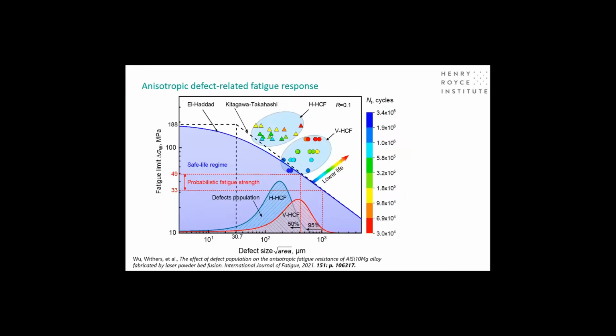And of course, if you know the distribution of defects and you're using CT to pick out those distributions of defects, you can start to make predictions about the fatigue life performance. Here you can see predicted life performance. So we have a fatigue limit of 188 megapascals, and we can see how you get a failure envelope here as the defect sizes increase.